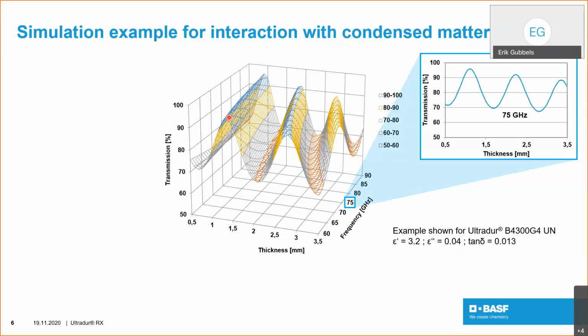If we have a look on one frequency, we've chosen 75 gigahertz, but you can choose any frequency within this range. And you can see that even within this frequency, there are 3 points or 3 thicknesses where there is destructive interference, and there are 3 points where there's constructive interference, showing this thickness dependency, which can go both ways. This is for a non-absorber. For an absorber, this behavior is less pronounced. However, it's still there, and therefore we decided to show you this behavior in one of its more extreme forms for you to understand that in all types of materials, such a behavior can occur, and therefore the thickness needs to be, let's say, thought about carefully.